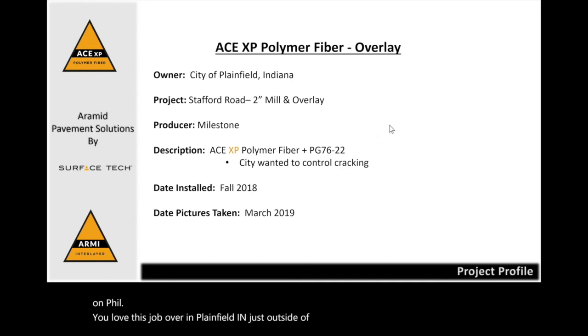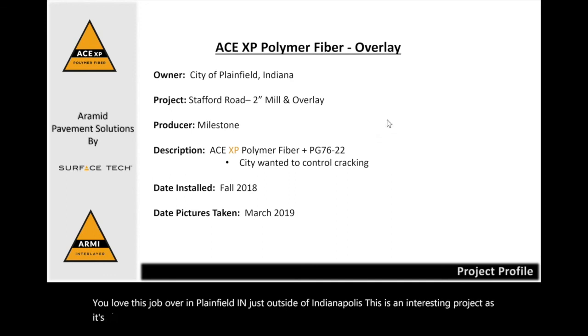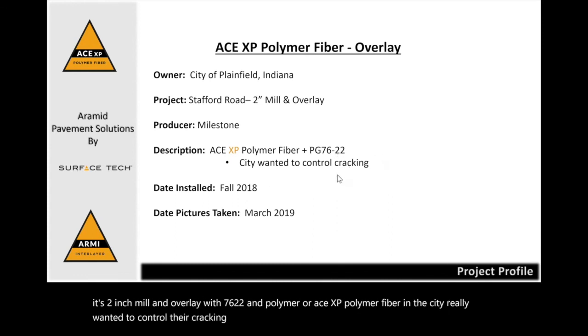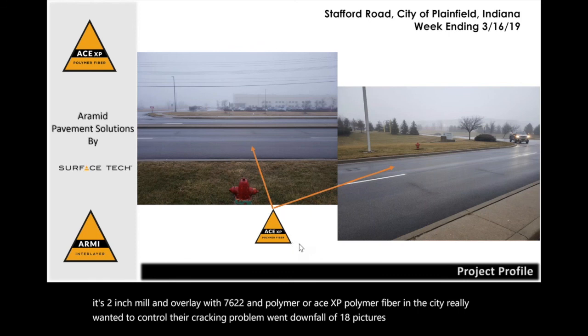This is an interesting project as it's a 2-inch mill and overlay with 7622 and polymer or ACE XP polymer fiber. And the city really wanted to control their cracking problem. Went down in fall of 18, pictures taken in the spring of 19.